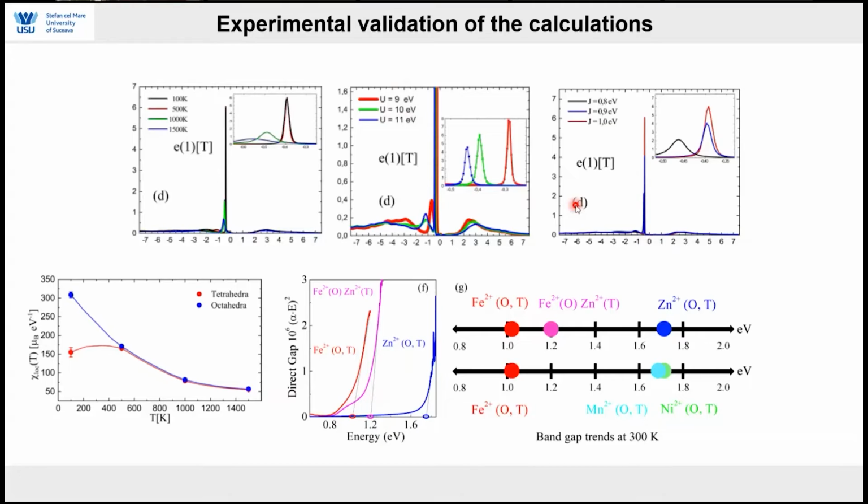But once you lower the temperature, the conduction electrons and the F electrons start to talk to each other, and at very low temperature the magnetic component, the spin of this electron, gets screened. In simple words, that's called a Kondo resonance. Now, what we see in our case, in this material, is a peak which increases as the temperature is decreasing.